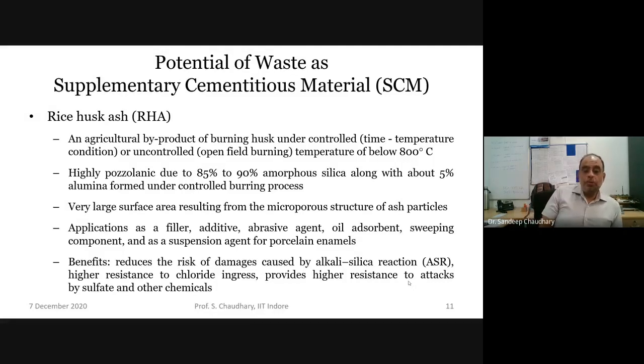The important point here is that what has been written is amorphous silica. So just the presence of silica does not matter. It should be amorphous in nature. There might be some other material which has a higher silica content, but if it's crystalline in nature, then it's not going to give us any advantage. So what is important is that we look for amorphous silica. And of course, it has 5% alumina also. And it has a large surface area, and that will result in higher reactions. And this forms from the microporous structure of the ash particles. It has a wide application such as filler, additive, etc.